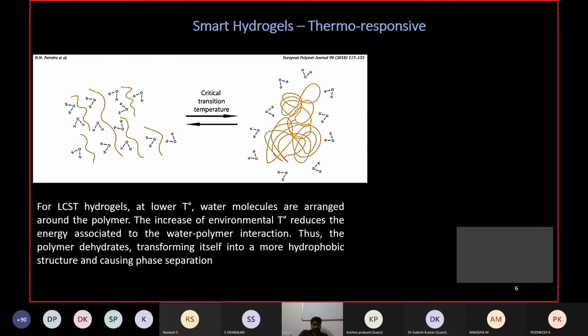I said at a lower temperature, when you are considering hydrogels that have a clear-cut lower critical solution temperature, water molecules are arranged around the polymer because they form a water of hydration around the polymer. Nothing but the hydrogen bonding on the strands of the polymer. So it is more like a layer of water on the polymer strands, and the temperature increase reduces the energy associated to the water polymer interaction. So some of the water molecules are expelled out. So when the polymer dehydrates, transformation occurs and there is more hydrophobicity.